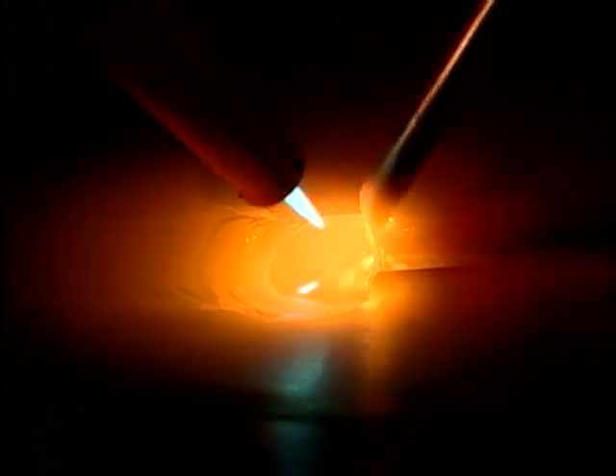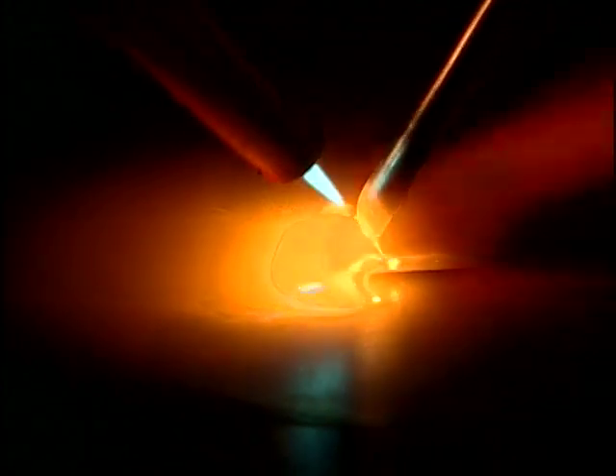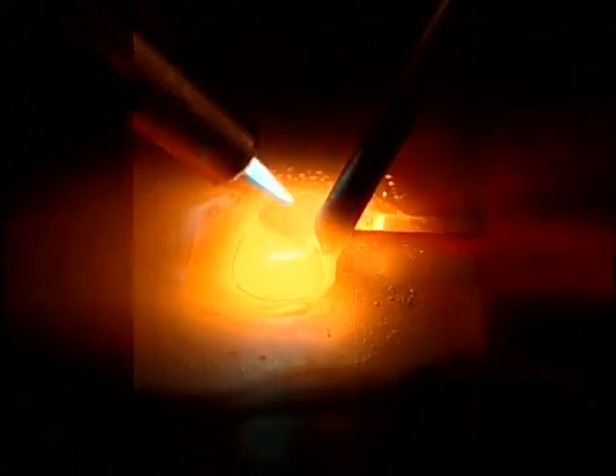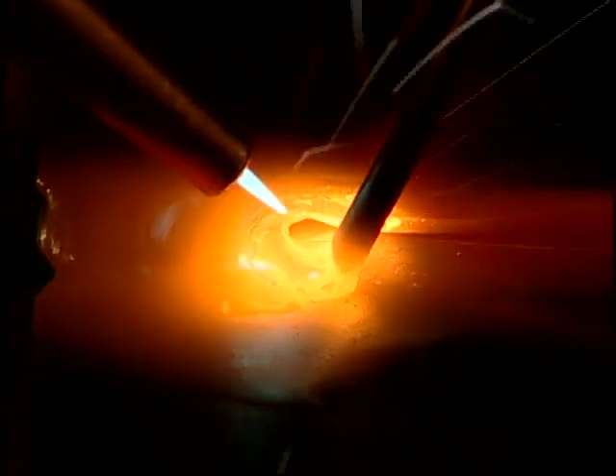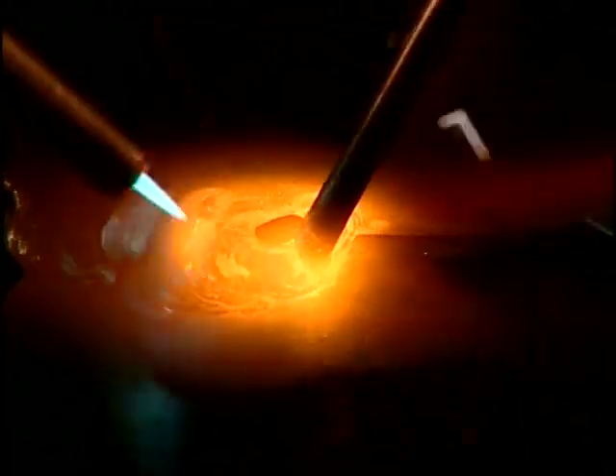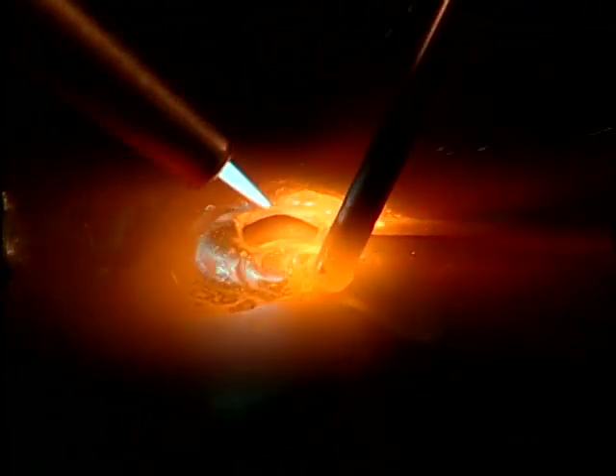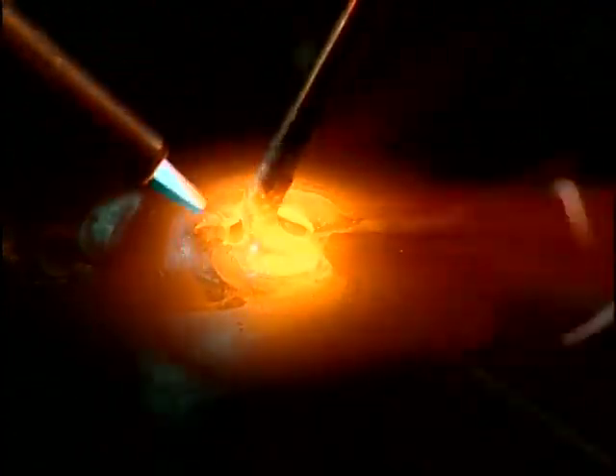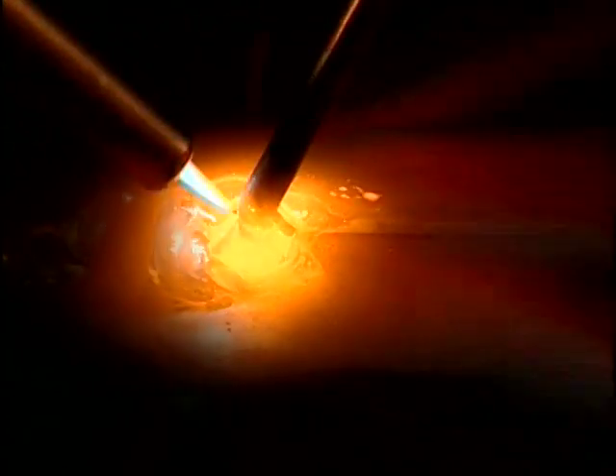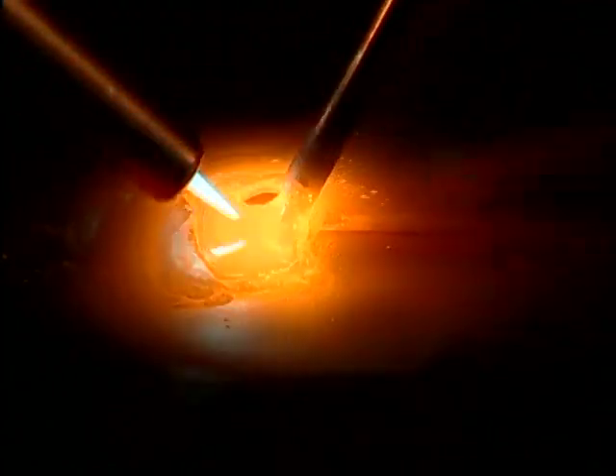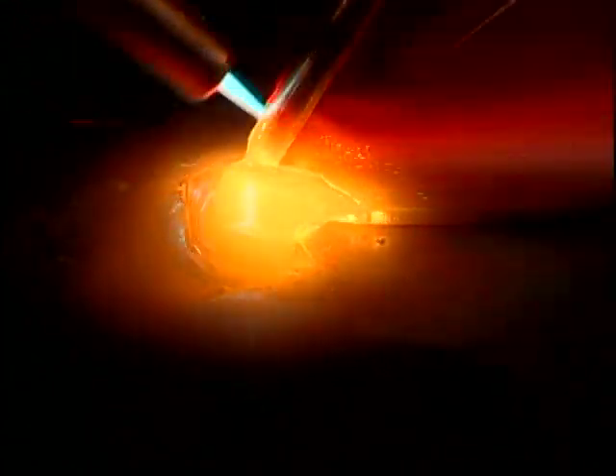Add the filler metal along the leading edge of the molten weld pool on the top plate. Surface tension will pull the molten metal to the center of the weld. If you are not adding the filler metal fast enough, a small notch may begin to form in the top plate as it melts away. Don't chase this notch with your torch. Increasing the rate at which additional filler metal is added can easily fill it.